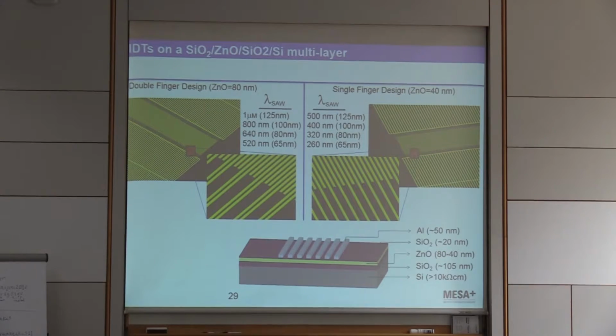We adjusted a little bit: we decreased the zinc oxide thickness to make it more advantageous for higher frequency Rayleigh modes, because they stick closer to the surface. And the last thing is that we went to, in this case, a highly resistive silicon wafer, so kind of quasi intrinsic silicon, because as you know, as long as you have free carriers around, they will screen the piezoelectric potential. So the more intrinsic your substrate, the better it is, at least from the surface acoustic wave piezoelectric potential point of view. And again, the design parameters are the same, because our template was also the same. Okay.